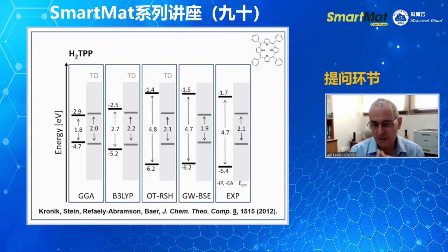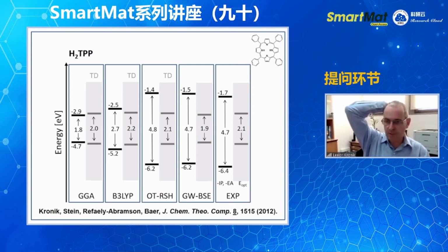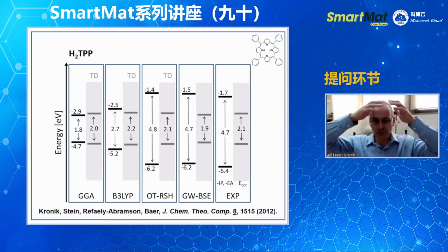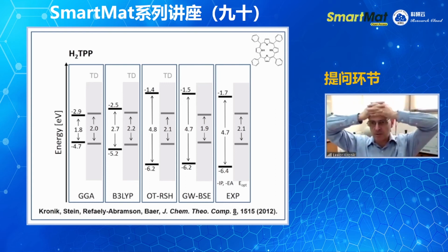Or maybe I can, in a similar way, optimally tune B3LYP, just optimally tuning the fraction of exact exchange in it. Here I would say, no, it's not a good idea to do that. There are a few papers that did that and they got specific properties correctly. This is not criticism, but generally it's not a good idea because the functional is not asymptotically correct. When you try to optimally tune a functional that is not asymptotically correct, you end up with a truly huge fraction of exact exchange because somehow the functional has to compensate for what's missing.